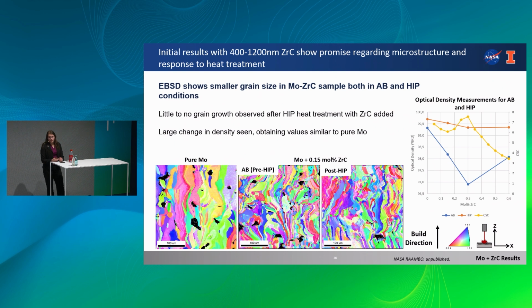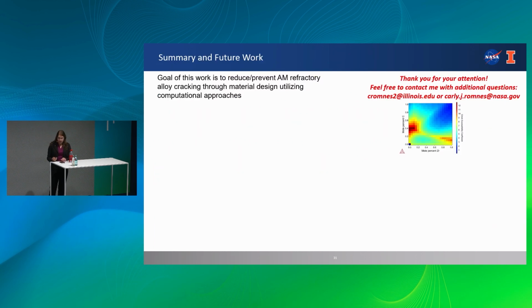and that should help improve our mechanical properties. If we look at the densities of the post-HIP materials, they all are pretty similar to the pure molybdenum, and we had a large change in the density, which is good. These are all responding to HIP, and a lot of that excess porosity is actually being closed. And like I said, this likely will result in better mechanical properties.